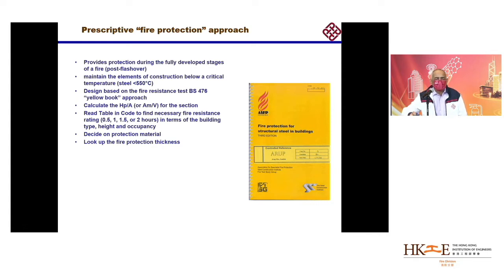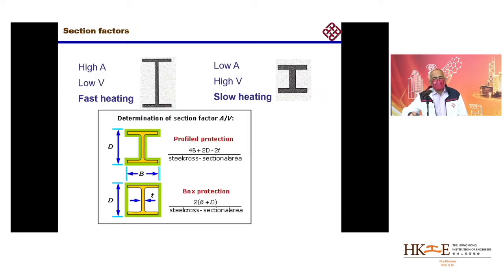And this is a book, the Yellow Book as it used to be called, that was used in Arup for designing structures in fire. The principle is that because you want to protect steel, when you see a thicker beam on the top right, the surface area is lower and the volume is higher. On the top left, you see a beam where the surface area is higher and the volume relatively lower. So the left beam will heat much faster in a fire, and the right beam will heat slower, because of larger volume and lower surface area, since the heat has to enter through the surface. So you can adjust the protection based on this section factor, the surface area over volume ratio.